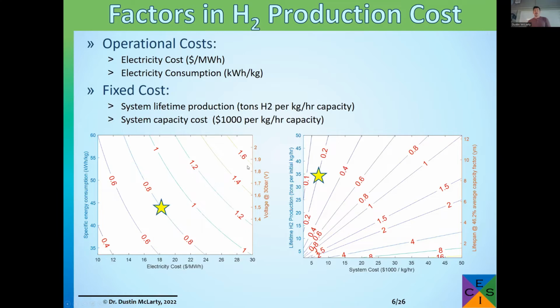On the system lifespan, we have to really assume some type of degradation and some end-of-life condition. So if we assume we're going to operate at fixed voltage and there's a linear degradation in the conductivity of our membrane, you're going to have a sort of 1/x production curve over its lifespan. In this example, I just assumed end of life meant you were producing 25% of your start of life, which works out that curve to an average of 46% of its initial capacity over its lifespan.